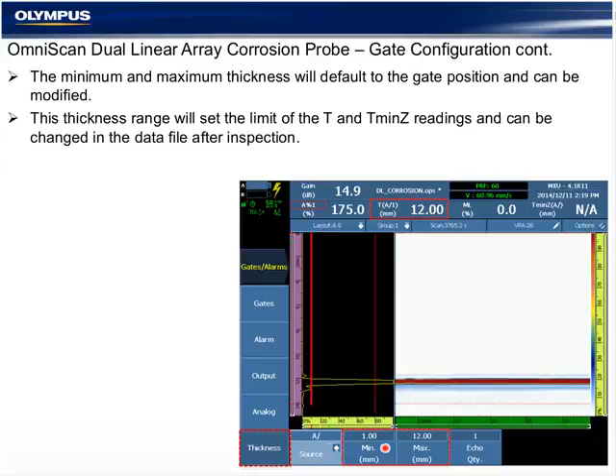By default, it will set to the width of the gate, and it is reduced by the operator. The number that appears in the thickness reading will not be outside the range of what is listed in the minimum maximum range here. It's normal prior to inspection conditions to set this from 1 to the nominal thickness and adjust it later during analysis mode or when inspection conditions are known.